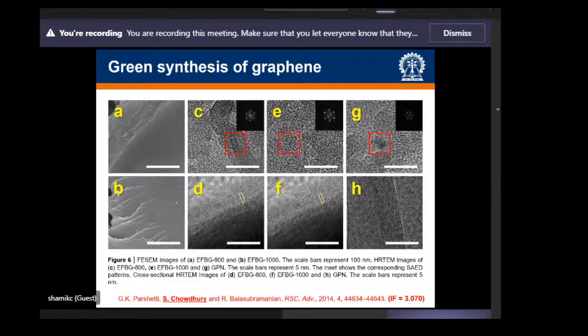Okay, then what we did is we looked at the high resolution transmission electron microscopy images. Both the samples, as you can see, presented densely packed hexagonal domains and perfect hexagonal atomic order, consistent with those observed for conventional graphene layers. And in addition, the corresponding selected area electron diffraction patterns, or SAED, that are shown over here confirm the presence of diffraction orders that are characteristic of well crystallized graphene layers.